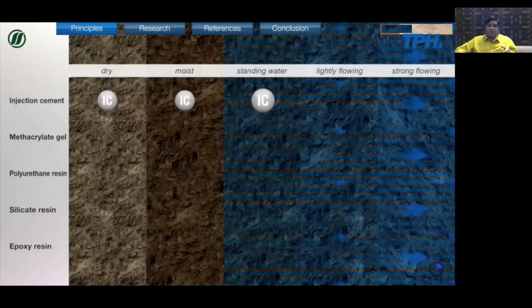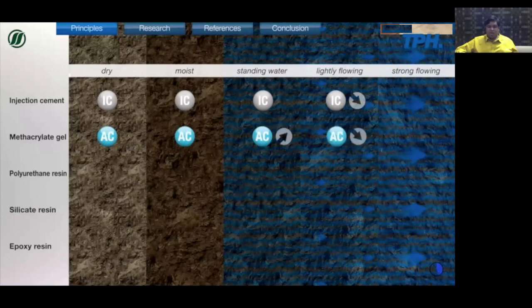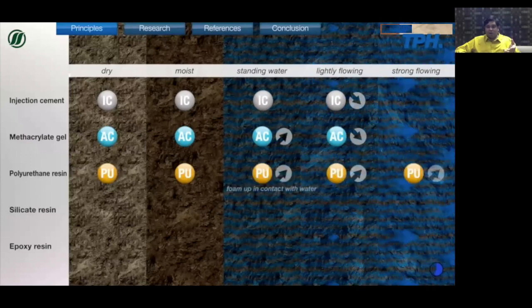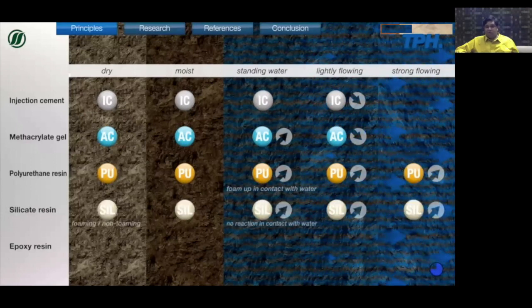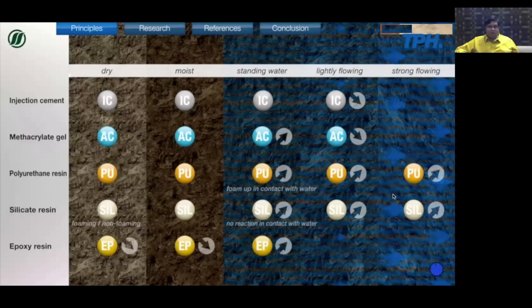Now, another area which we have to really look at, especially in both crack injection as well as soil stabilization techniques, is the flow of water. For example, if the conditions in which you're injecting are dry, then you can pretty much use any one of the four or five different resins that we took a look at. So you can use injection cements, the methacrylate gels, the polyurethane, the silicates, as well as epoxies. The same goes for moist conditions as well. Even our epoxies today, up to a certain degree, can tolerate moisture very well.